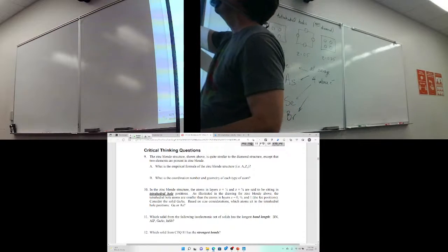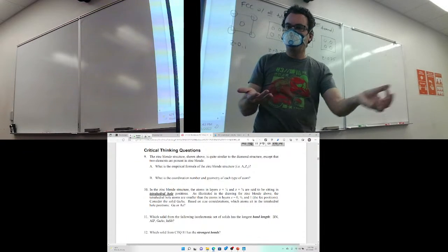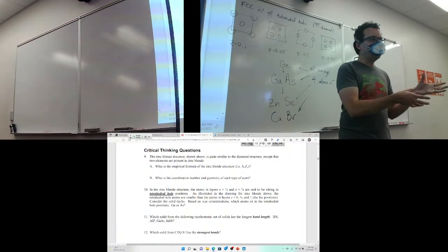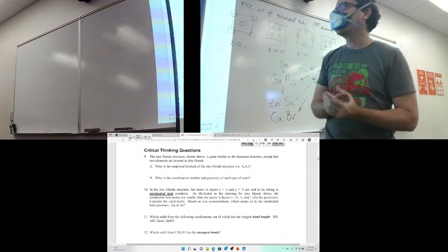So 9A, the empirical formula, if you use just generic letters, is A1Z1. It's just one of each atom, so a 1-to-1 ratio. If you count the atoms, there's 4 of the FCC position atoms, and 4 of the hole position atoms. Whether you're in a hole or in the FCC positions, every atom will touch only 4 other atoms. Doesn't matter which position you're in, you always touch 4. So the coordination number is 4. The geometry is tetrahedral, same as for diamond.